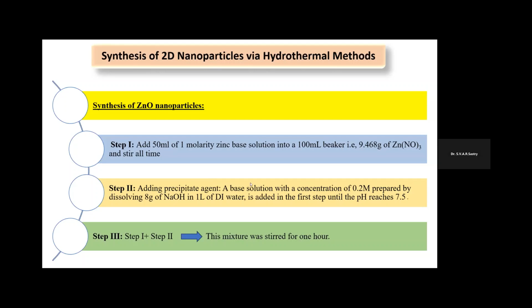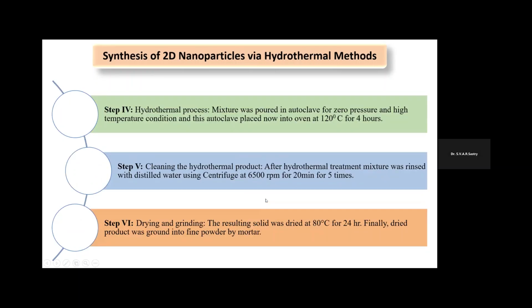So then let's see the synthesis of nanoparticles using this hydrothermal method individually. Start with zinc oxide nanoparticles. We added 50 ml of 1 molar zinc-based solution. Then zinc nitrate was taken, then it was precipitated, and the mixture was stirred. Then we used hydrothermal processing for synthesis of the nanoparticles, and we kept a temperature of 120 degrees Celsius for a period of around 4 hours.